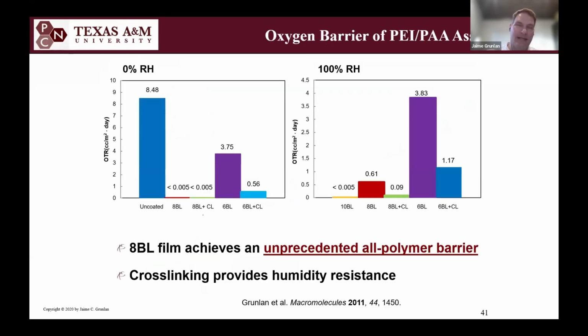And when we did layer by layer assembly with those two polymers, an 8 bilayer coating that was about 1 micron thick had an undetectable oxygen transmission rate. So it's a pure polymer, and I can't measure oxygen going through it. Of course, oxygen is going through it, but at a very, very, very slow rate.